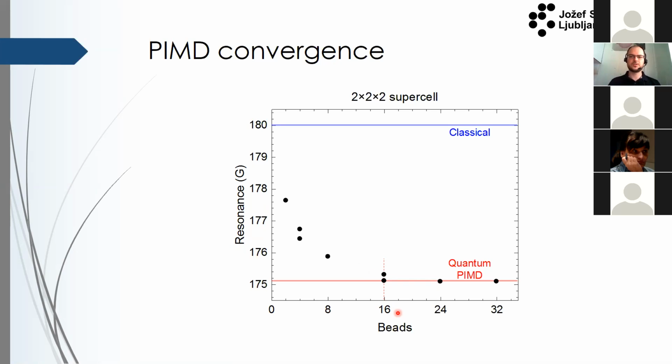So lower temperatures need more beads, and usual values are anything from about 10 beads up to 150 beads, something like that. That's what's usually done. It is somewhat limited though by computational power. So for small molecules, you can do much more beads. This was a relatively large supercell still. But it seems that in terms of the experimental observables that we're interested in, it is converged. You have to converge it for every case separately, and for every temperature separately, in principle.